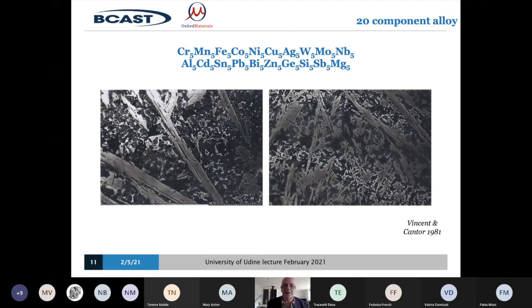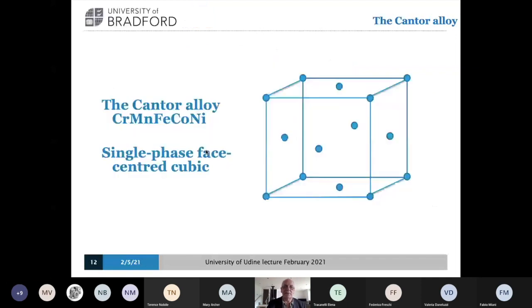We discovered that one of the crystalline regions in this material consisted of 5 components: chromium, iron, nickel, cobalt, and manganese in equal proportions in a single phase structure, and it's called a Cantor alloy. So here is the structure. Let me explain it. The Cantor alloy is 5 components, these 5 components in equal proportions. That's 20% of each, a fifth of each. And they exist in a single phase face-centered cubic structure.